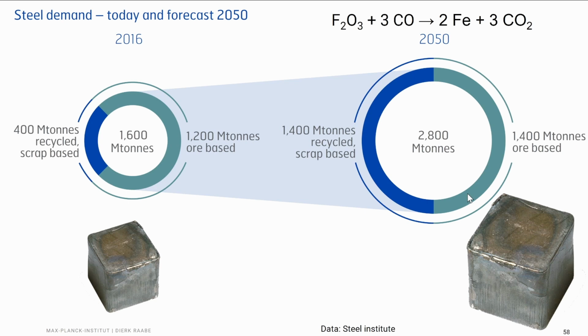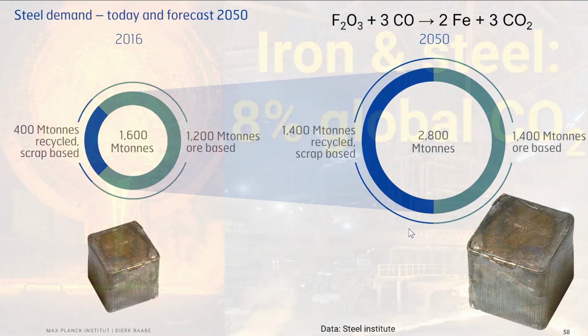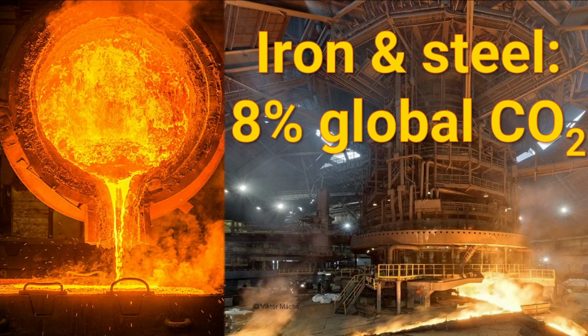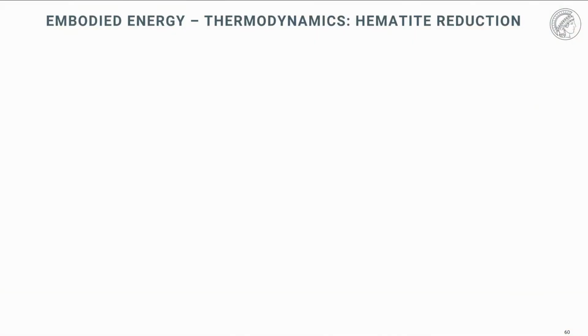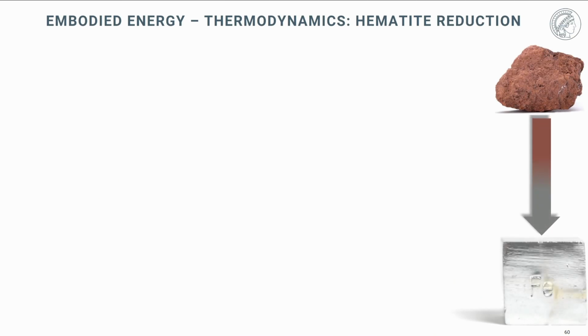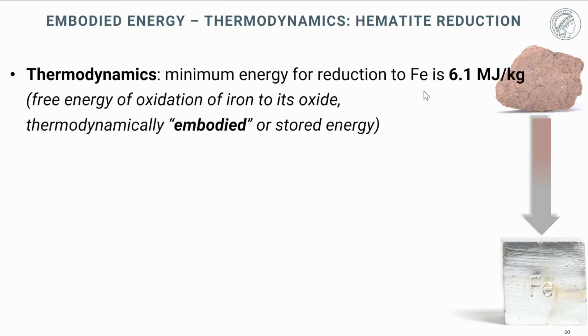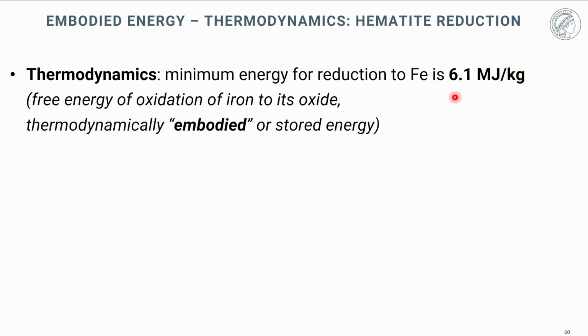This incredibly large amount of material is a big environmental burden, because the primary synthesis of iron from its ores, like here hematite, is made by carbon carriers. That means the reductants are carbon carriers to produce your iron, and that gives, in the mass balance, very high CO2 emissions. That is the reason why iron and steel making stand for about 8% of the global CO2 emissions. When we look just at the thermodynamic limits, we see that we have about 6 megajoules per kilogram that is embodied in the iron oxide.